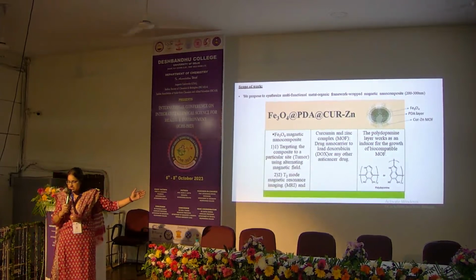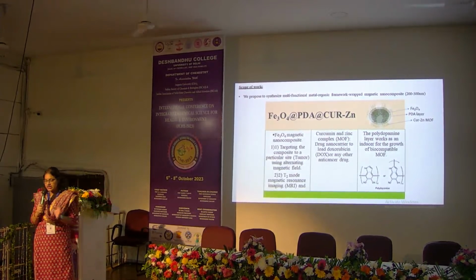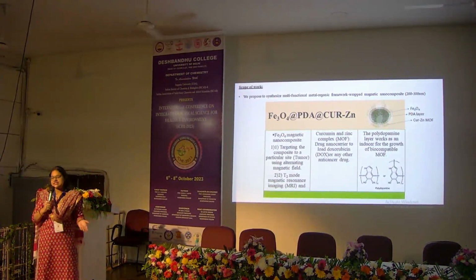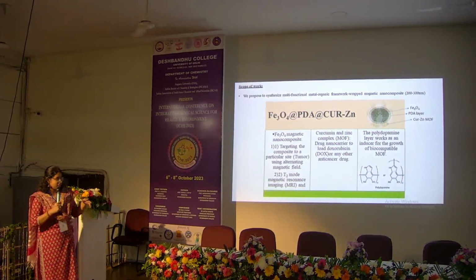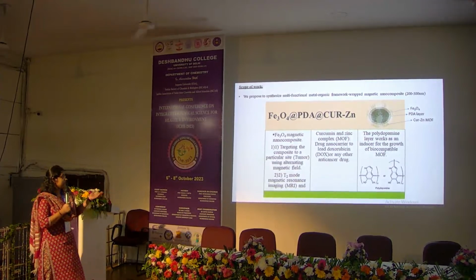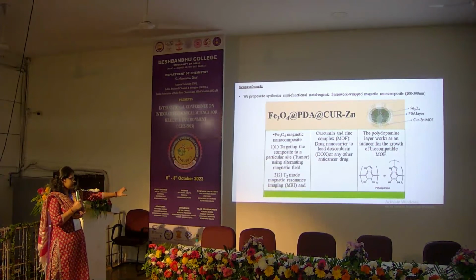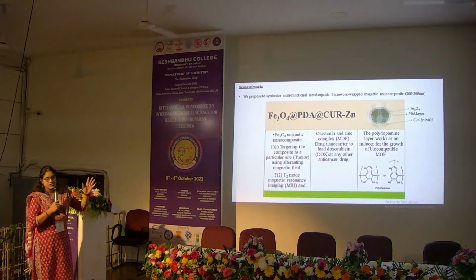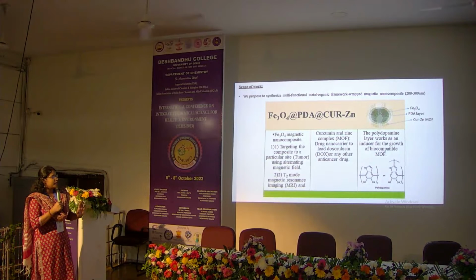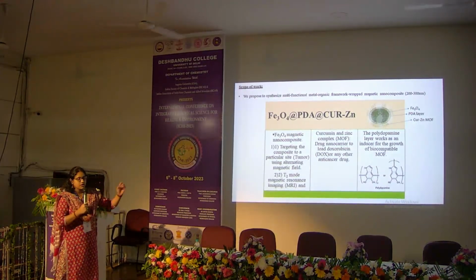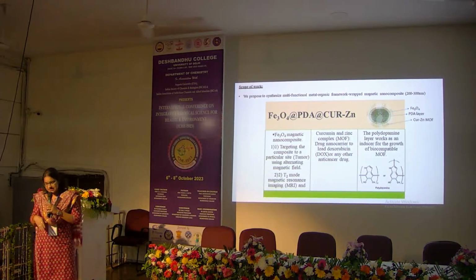Zinc is the metal source and curcumin is the linker, and curcumin itself acts as an anti-cancer drug and in anti-inflammatory disease as well. So iron oxide can be used for T2 mode magnetic resonance imaging. Polydopamine, made from dopamine, can be used as a coating and is also pH sensitive.